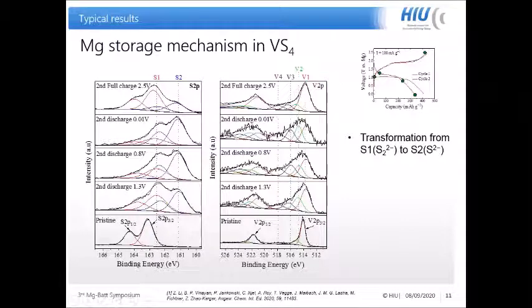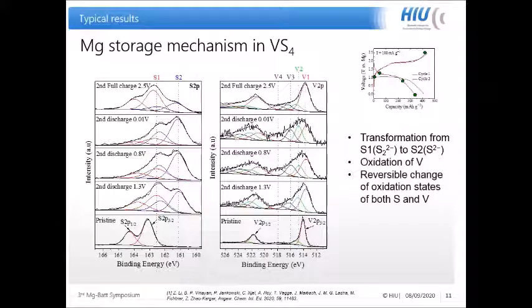Yeah, I think the question was rather whether maybe magnesium sulfide has formed. But if this is very small, you won't see it in an XRD, right? And it would also not appear as such in the XPS. Yes, this is difficult to see, because in the XPS we cannot distinguish the vanadium-sulfur bond and the magnesium-sulfur bond. So this is the problem. So this might be a potential degradation mechanism.